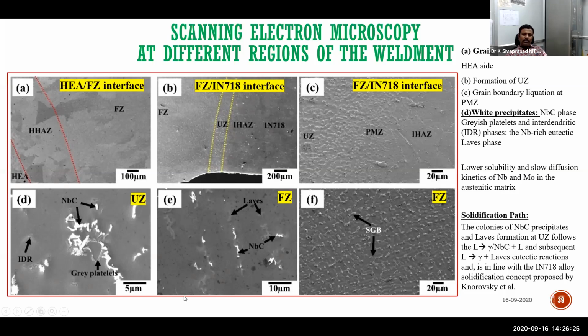Otherwise, it is similar to the microstructural features which we can conventionally get from typical Inconel 718 weld fusion zones, such as formation of small Laves phase and NbC, interdendritic region precipitates, and gray platelets, carbides, NbC carbides, Laves phase. These are all very, very common in fusion zones of Inconel 718. Normally, Inconel 718 weld efficiency used to be something like 60% or so only. But here we could get relatively superior compared to that.